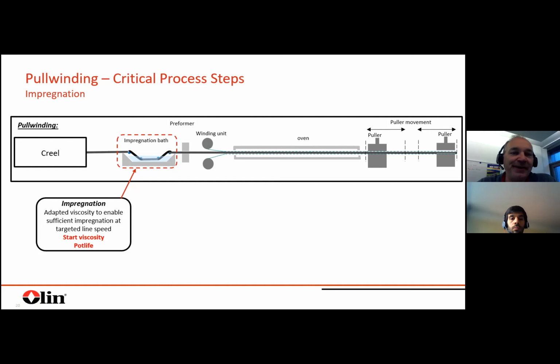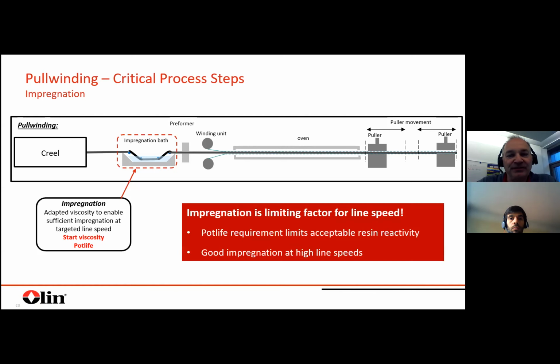So, and here the key criteria from resin point of view, it's a start viscosity of the resin themselves, and for sure the pot life if you are using an impregnation technology like an impregnation bath. But what I also would mention from my point of view is the impregnation is also the limiting factor for the line speed of the production.